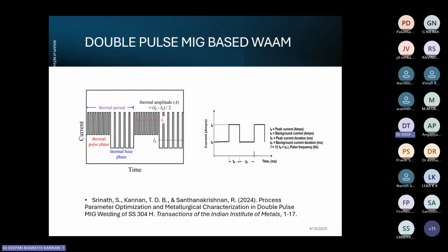This is a schematic of double pulse. Double pulse is a recent advancement with respect to MIG-based WAAM, where we'll be using a thermal pulse phase as well as a thermal base phase. Because of the change in the thermal pulse phase and thermal base phase with microsecond variation, we'll have a stirring effect in the molten pool. As a result of that, it will help us to minimize porosity, and also it will help us to minimize crack formation, and also it will help us to fragment the dendrites, leading to fine grains.